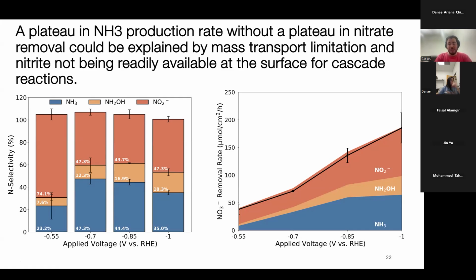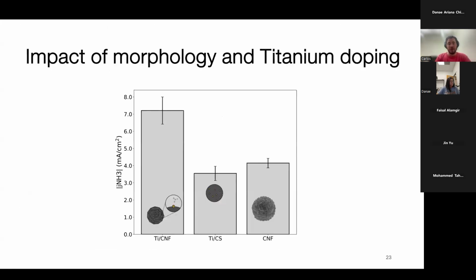But we see something pretty similar as well with where our nitrogen is going. You can see that, even though a lot of it goes to ammonia, that contribution plateaus after 0.85, and the nitrite grows as well as the hydroxylamine. So this further corroborates our hypothesis that we're having some mass transport limitations, and we're addressing that right now by moving to an electrolyzer that has flow channels and flow architecture.